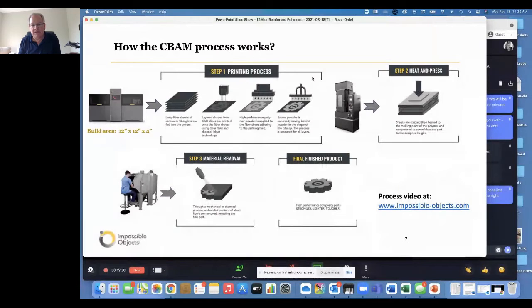The way the Impossible Objects process works, known as CBAM, composite-based additive manufacturing, is a 3-step process. Starting with step 1, we take those pre-preg sheets and feed them onto a print platen, and using an inkjet print head with 600 dpi resolution, we take the slice file from your CAD file and wet out the image onto the pre-preg sheet. After that occurs, the sheet automatically flows underneath a waterfall of either a thermoplastic powder or an epoxy thermoset powder,